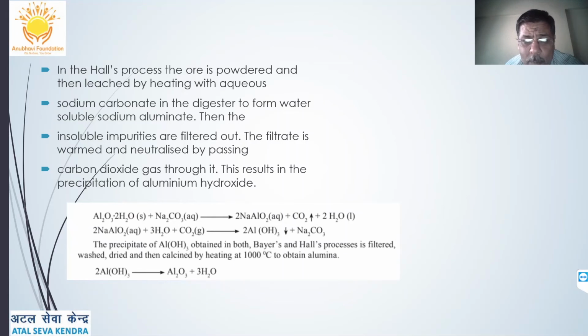Now coming to Hall's process, the ore is powdered and then leached by heating with aqueous sodium carbonate. Al2O3·2H2O reacts with sodium carbonate to form sodium aluminate, which reacts with water, and carbon dioxide is passed through it for a long time to form aluminium hydroxide and sodium carbonate. The precipitate of aluminium hydroxide, which is obtained in both Hall's method and Bayer's process, is then filtered, washed, dried and then calcined by heating at 1000 degrees centigrade to obtain pure alumina.